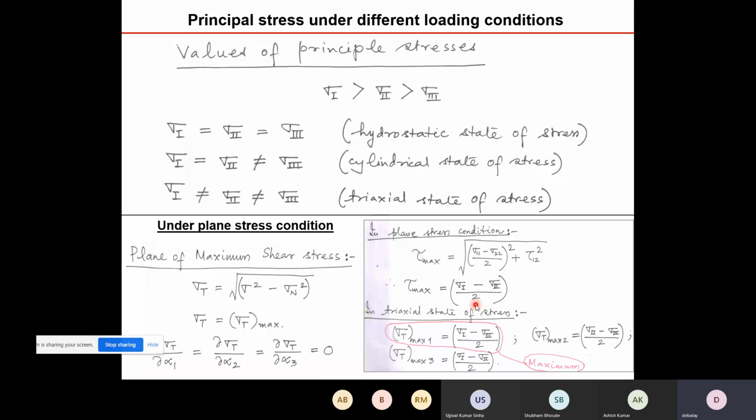And that is why the shear lip that forms occurs at a 45 degree angle, because metal tends to shear at 45 degree. Similarly, when fracture occurs under shear, that is 45 degree. Even the slip bands that form inside, if you do a loading of a single crystal, you will find that is 45 degree with respect to the loading direction, because maximum shear stress occurs at a 45 degree angle. Sometimes it may not be absolutely 45, but close to that.